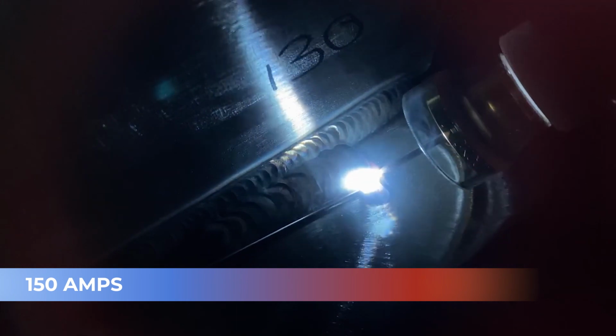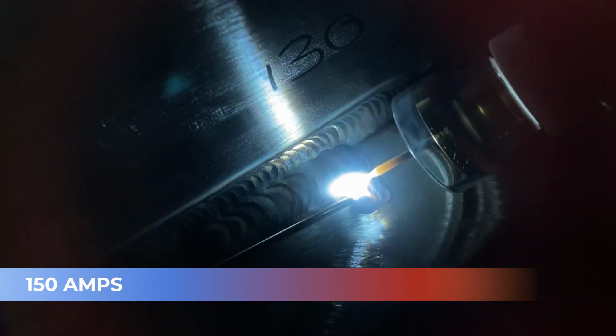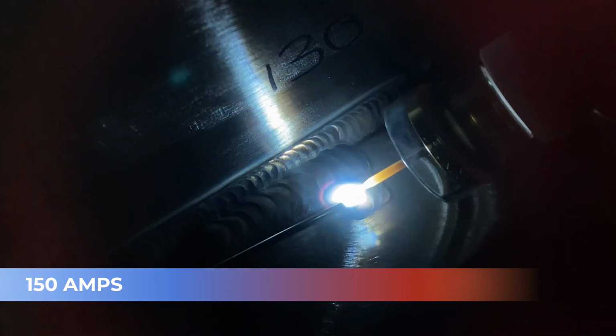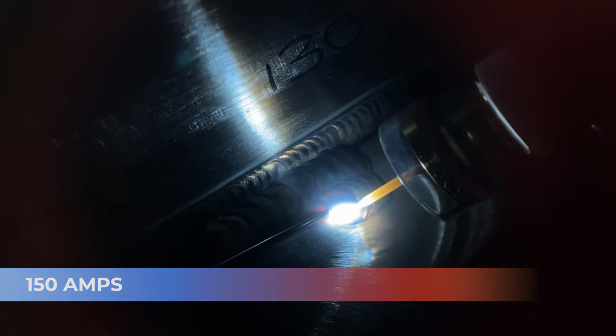Same thing again, we're going to step it down to 150. Notice immediately how the base metal is consumed. And this is what I mean by flow. It's flowing nice. I'm able to manipulate the weld how I see fit. And I'm able to push as much filler in as I want. And it will still be a quality weld. That's when you know you're in the sweet spot.